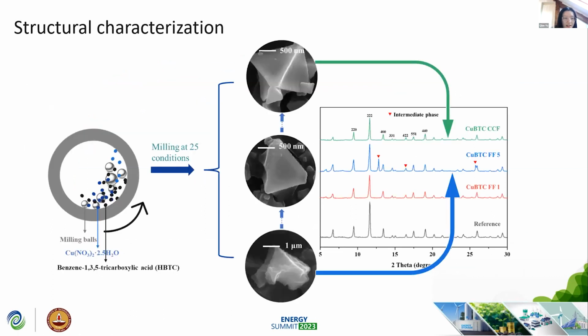In addition, we also did the characterization of our samples synthesized by the mechanical method. We did the 19 experiments generated by the DOE and the actual 6 experiments, and then we found out the formation of the copper BTC is through an intermediate phase. This is also validated by the SEM images and XRD patterns. As you can see, this is the intermediate phase. As also seen in the XRD pattern, it has 3 extra peaks, which means the existence of the intermediate phase. After growing the crystal, we can get a fully synthesized crystal like this. In this sample, the XRD pattern is clear and is nearly the same as the reference one.